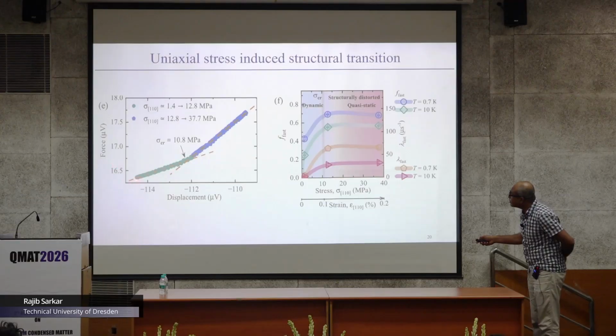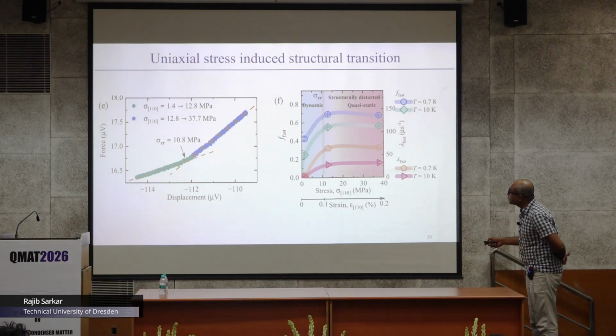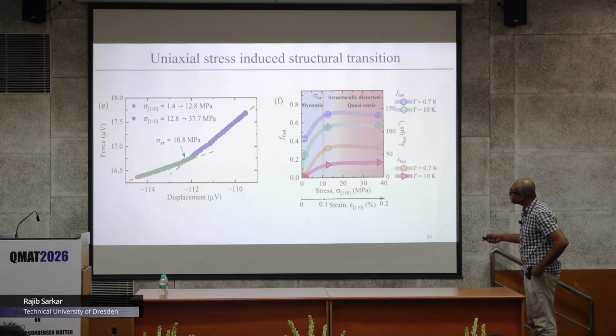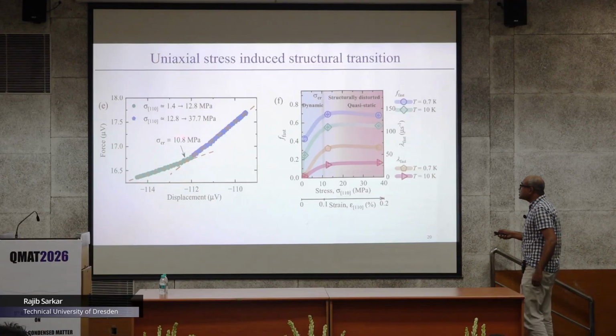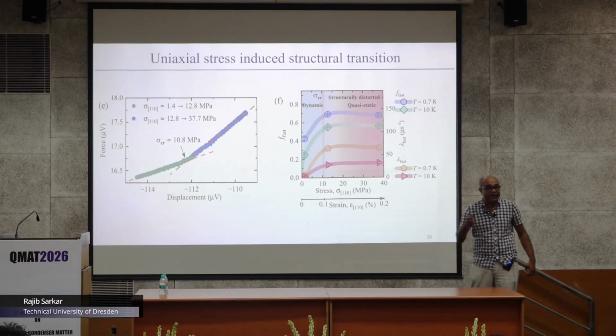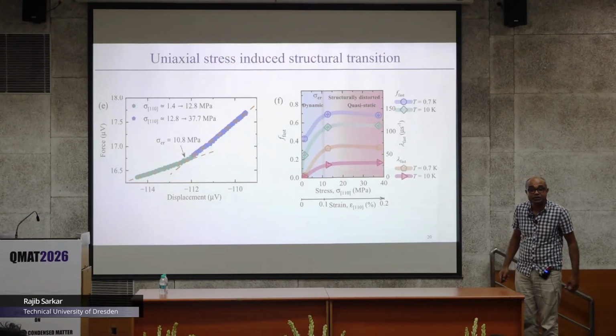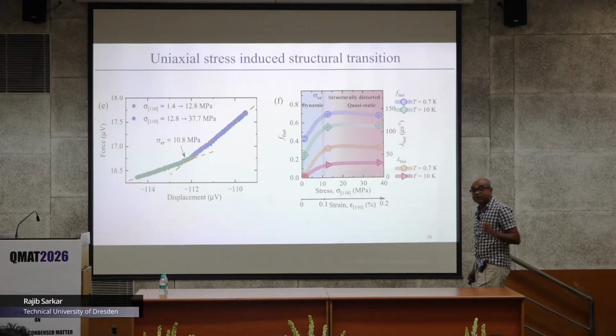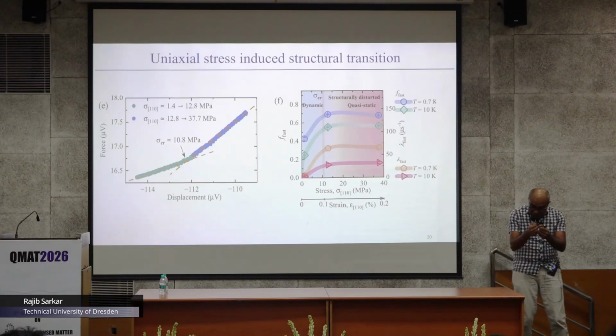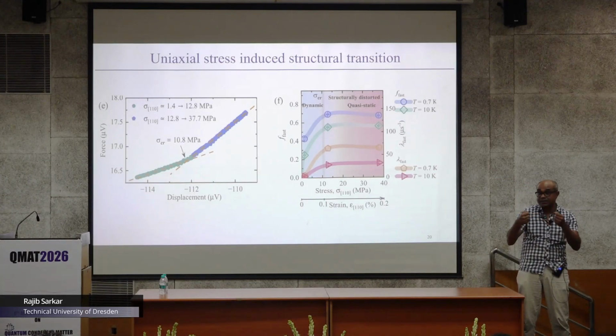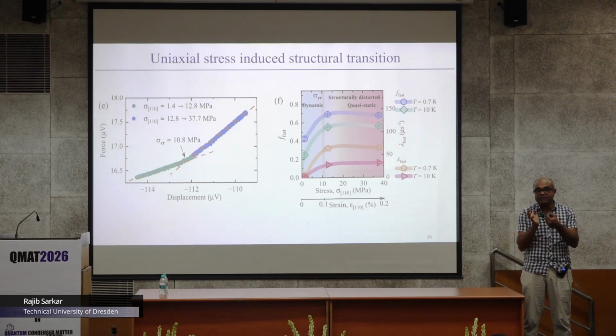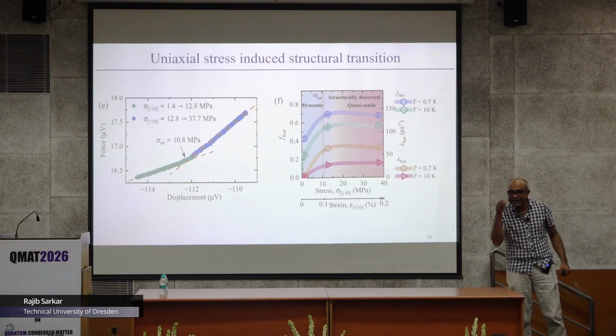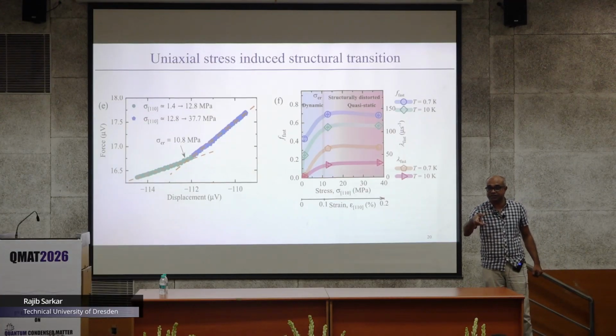And if you make a plot, now you see, as the displacement changes through the force, which is applying the voltage, there is a linearity. But as soon as we go to 10.8 megapascal or near about this pressure, you have a slope change, and that slope change doesn't recover. What does it mean? That means I am changing my pressure in one particular direction, the other direction, and I am slowly increasing the displacement values, and now suddenly there is a change of my displacement, and that is only possible if the crystalline symmetry is changing in the system.